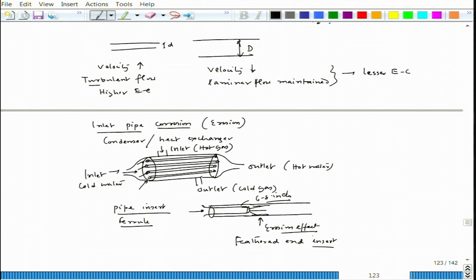So what is the advantage? The advantage is, of course, the main tube end, that is, this is the tube, one end is here, another end is here. The main tube end, if you consider the inlet end, will not get any erosion corrosion. The effect would be very, very low, in fact almost negligible. Now the entire erosion corrosion would be taken by the ferrule. If you see a huge erosion corrosion effect on the ferrule and it is trying to affect the main pipe, we can take out the ferrule and replace it with a fresh ferrule.